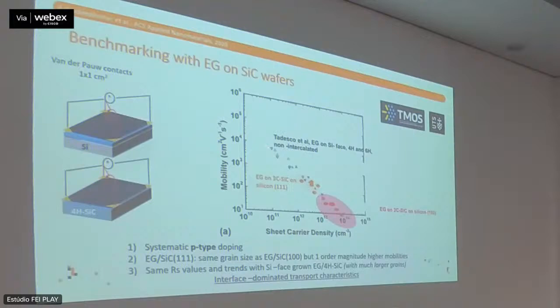Now, if we do the same type of evaluation on our graphene, which has the 100 nanometer grain size I explained, another important preamble, this is my flake size, so grain size. It turns out that our graphene with much smaller grain size also sits pretty much on the same trend. Indeed, the sheet resistance that we get out of our layers is pretty much comparable to what you would get on silicon carbide wafers, and this is very important. What really happens here is that all of our points, and these are the one-one-ones, the surface on one that we use, and these are 100, differ by the fact that they find themselves all at the high end of sheet carrier density.